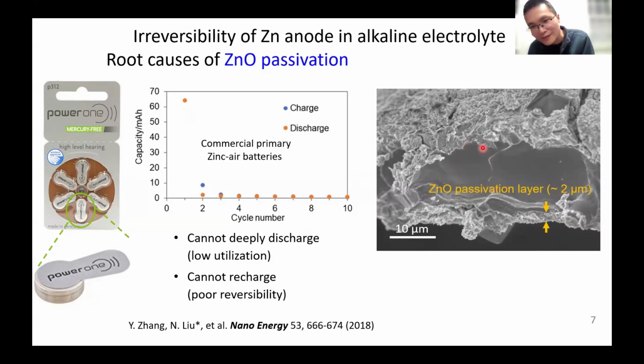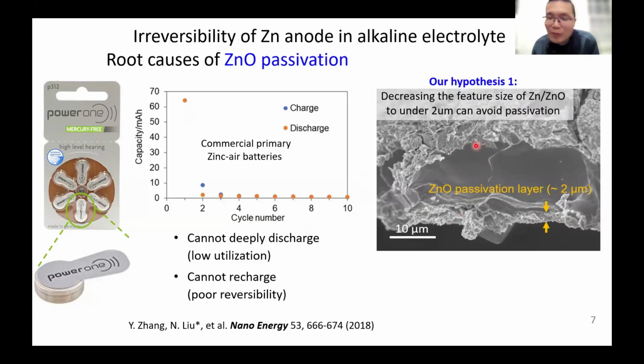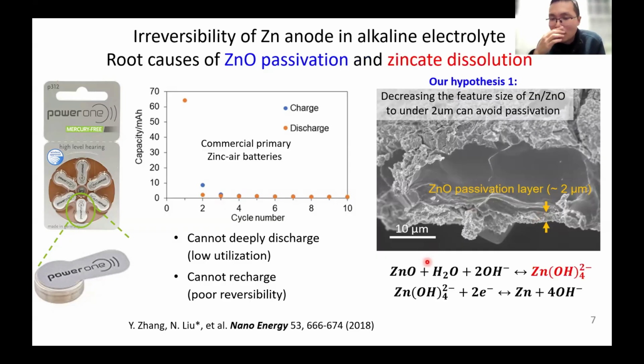But that also gives us a hypothesis. If we can reduce the feature size of zinc to below this critical passivation thickness, then we can fully convert the zinc to zinc oxide and then back to zinc without the passivation, because you will fully convert before this thickness of zinc oxide is built. That's the first hypothesis.